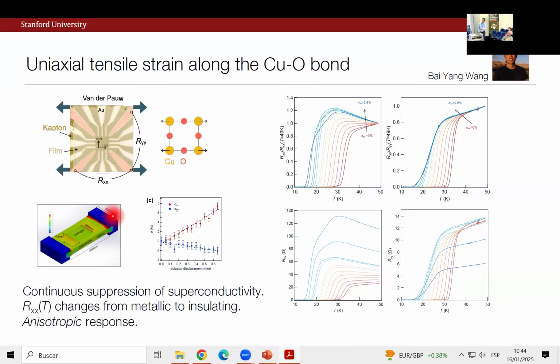If we look in the same device, in the transverse direction, that is, we stretch this direction, but we measure in this direction, we see 2 things. One is the normal state resistivity goes down. Again, intuition is reasonable that in that direction we're bringing the atoms closer together. But also TC is coming down. And so I just show this here normalized. This is an excursion from 0 to about 2.58% strain.